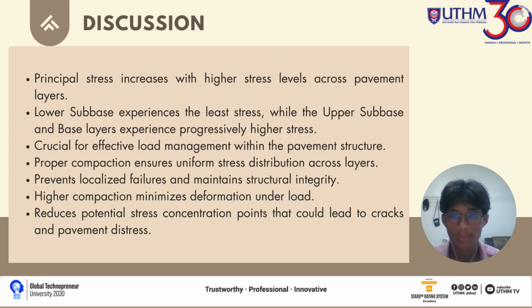From Figure 2, principal stress increases with high stress levels across the pavement. The lower subbase experiences the least stress, while the upper subbase and base layer experience progressively higher stress. This is crucial for effective load management within the pavement structure. Proper compaction ensures uniform stress distribution across layers, prevents localized failures, and maintains structural integrity. Higher compaction minimizes deformation under load and reduces potential stress concentration points that could lead to cracks and pavement distress.